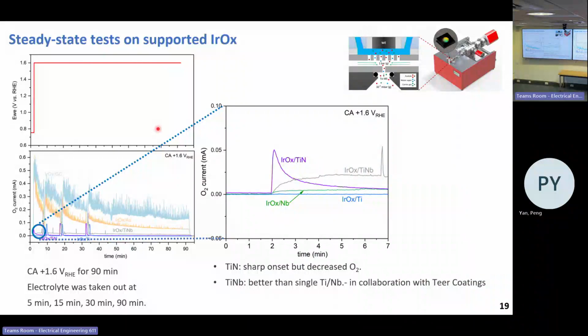So this is the electrochemistry mass spectrometry data on iridium oxide supported onto different supports. There's no doubt that iridium oxide has the highest activity when supported onto bare glassy carbon and gold, because they are the most conductive substrates. If we zoom in to look at this titanium-based support, we can see there is a really sharp onset of the oxygen signal, and then it decreased quite a lot, down to zero. Iridium supported on titanium niobium alloy has quite stable activity and higher activity compared with pure niobium and titanium.